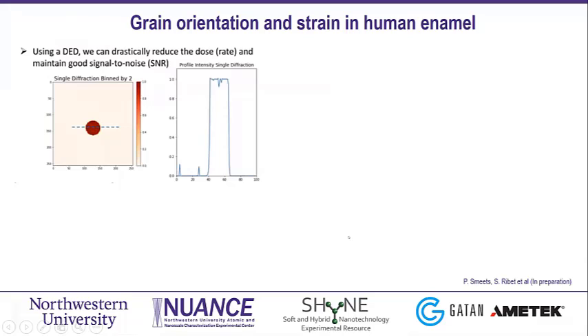But how about in terms of applications, right? So one nice application here is done by our TEM manager here, Dr. Paul Smeets. He used that 4D STEM to combine all those things, right? Looking at soft materials, which is a human enamel here, using 4D STEM and reducing the dose using the direct detector. So this is an example of a diffraction pattern from the vacuum where you can see a very good signal to noise ratio where you can definitely use that to extract information from your sample.